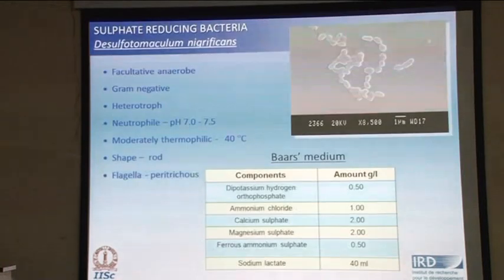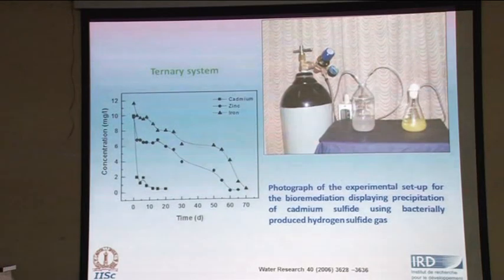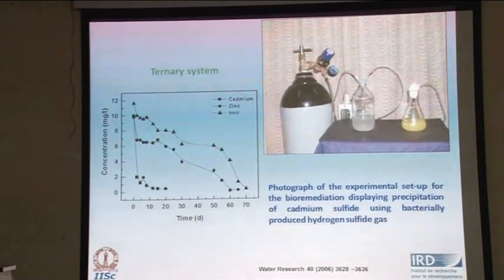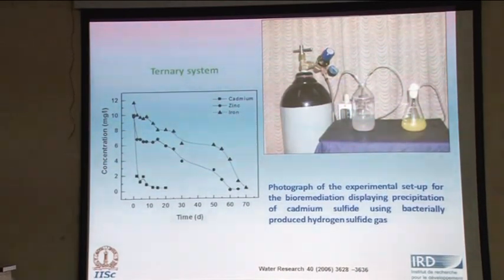So you can see that cadmium is precipitated first, followed by zinc, and finally the iron. So if you look at the solubility product of the sulfides, they follow the same principle. So you can use this to actually do a selective precipitation.